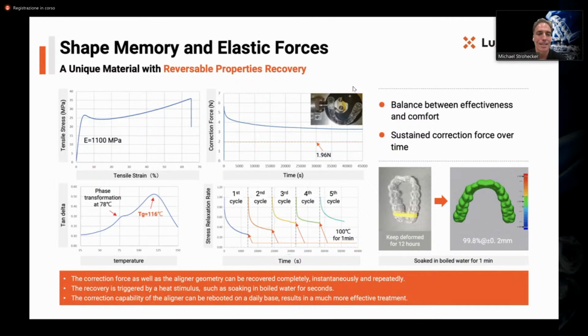The glass transition temperature is the temperature at which the material starts to soften, and it's not a cutoff. It does start earlier. Our glass transition temperature is close to 120 Celsius or 116 Celsius. Other materials have been much lower than that, which means that once you put it in your mouth, it starts to soften. And when it softens, it relaxes. And when it relaxes, it doesn't apply forces.